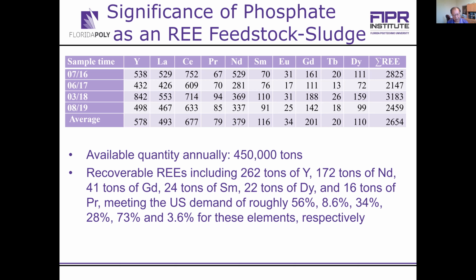So these numbers represent, as you can see, much of the U.S. demand for these elements. For yttrium, it's like 56%. That's the highest. For others, we have 8.6%, 34%, 28%, 73%, and 3.6%. So this one stream is a very significant source of rare earth elements.